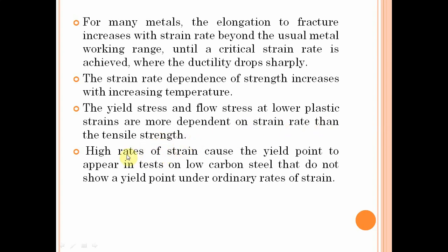The last point: high rates of strain cause the yield point to appear in tests on low carbon steel that do not show a yield point under ordinary rates of strain.